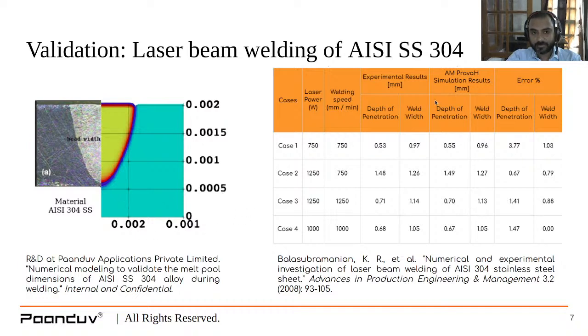And for different combinations of laser power and welding speed, so there are 4 such combinations, we have the experimental data available for the depth of penetration and the weld width, and we took that experimental data and we simulated the same set of parameters in AM PravaH, and we compared the results. You can see that for the depth of penetration, the error is under 4% in the worst case.